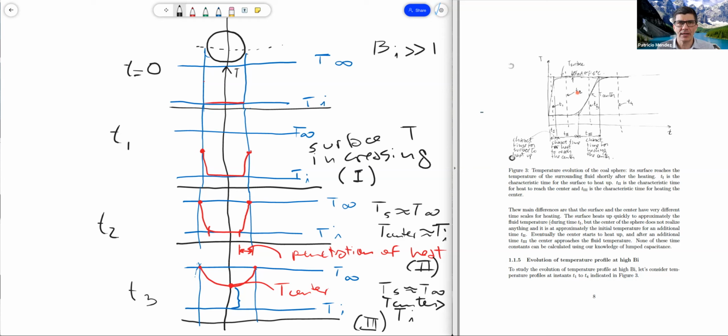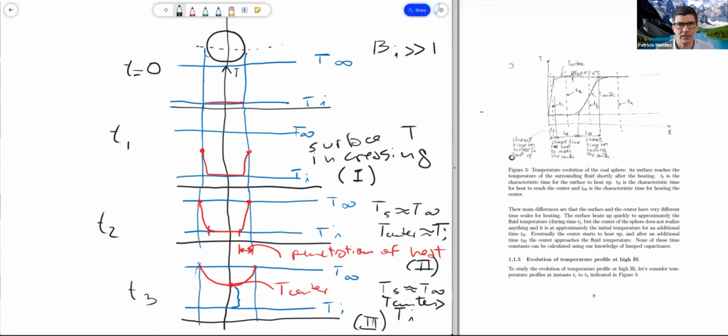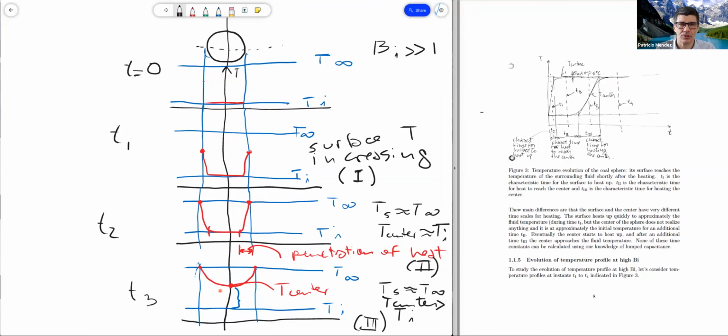The Industrial Revolution came and people wanted to make maybe not swords, but shafts for steam engines, and bigger and bigger. And when they wanted to quench this to make it hard and strong, they would get these fast transients on the surface and the material would be quenched on the surface, all right. But inside, it was a very slow quenching. In this case, we did a heating, and quenching is cooling down, right? It would be very slow. And the traditional steels would not quench and would be weak.